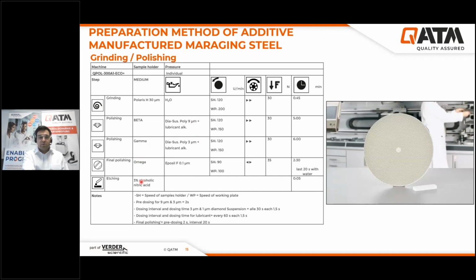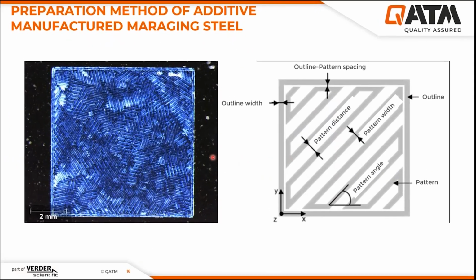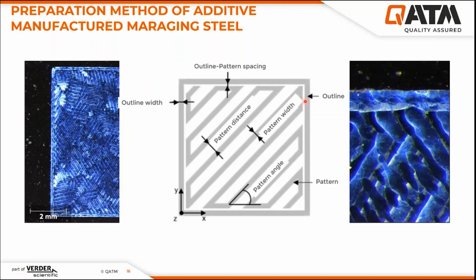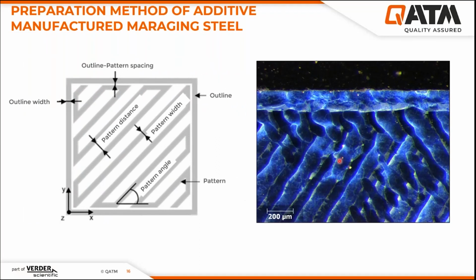We etch the samples with 3% alcoholic nitric acid for just 5 seconds. After that, we can see the structure under a stereo microscope. And as you can see here at low magnification, we can see the outline, a white outline pattern, and also the spacing between the outline and our pattern. When we go to higher magnification, we can see the spacing between the pattern and also the pattern angle, and different parameters can also be measured on these stereo microscope images.